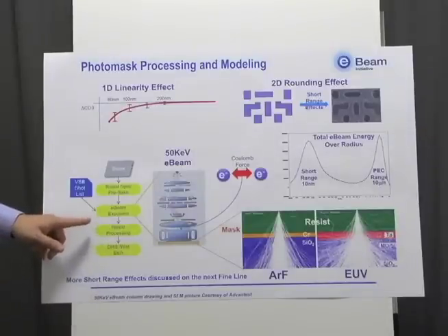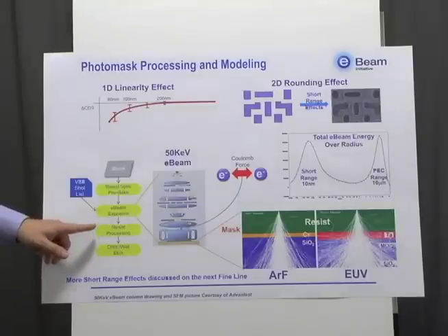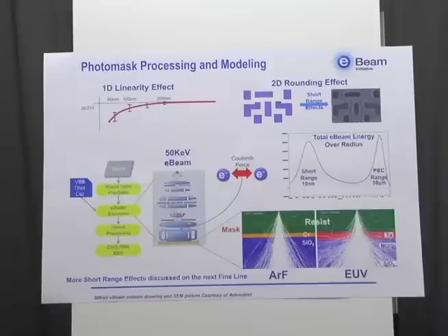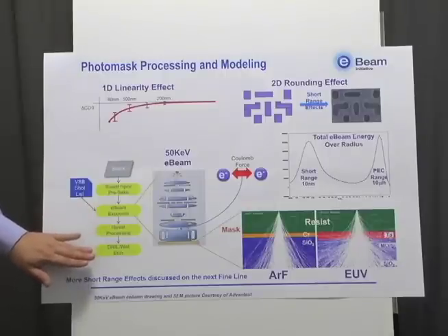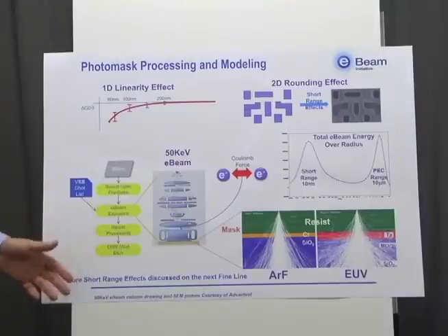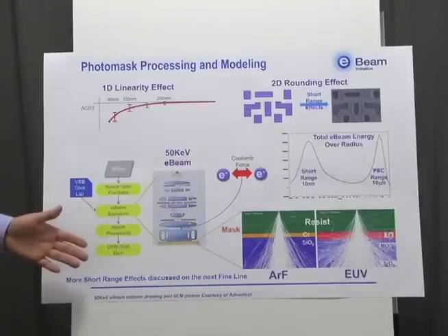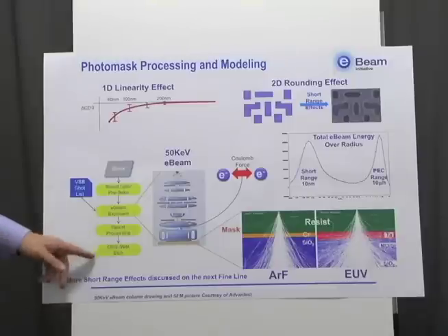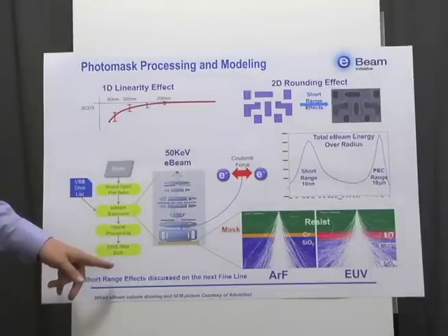And there are a lot of steps that go on here, which we don't have time to discuss in this session, but in the end, the result are resist lines, which protect the underlying mask, and resist spaces, which expose the underlying mask. That will form the basis of the final mask pattern. Finally, we then go to the etch process, where some more neat chemistry then transfers the pattern set up in the resist to the actual physical mask, where you etch the chrome or the glass or the absorber, depending upon the type of mask that you're making, where the resist isn't present. Then you remove the resist, do some more clean steps, mount your pellicle, inspect your reticle, and then ship your reticle to your final customer.